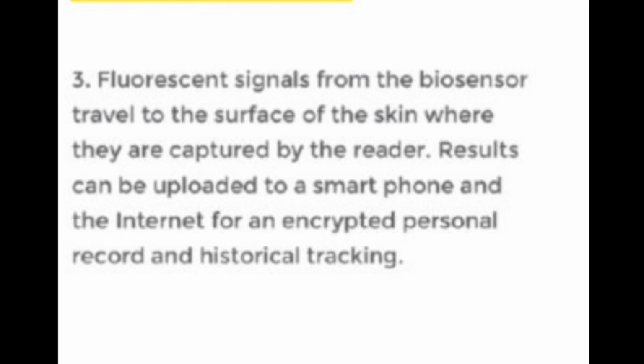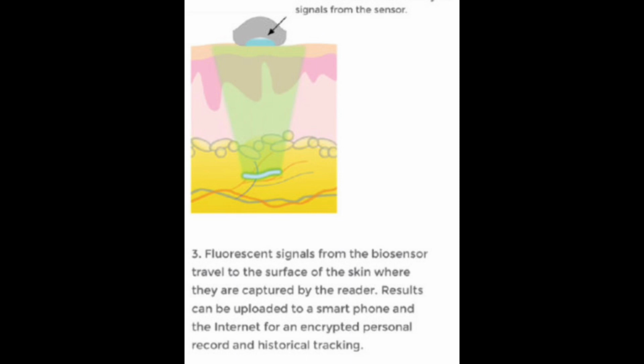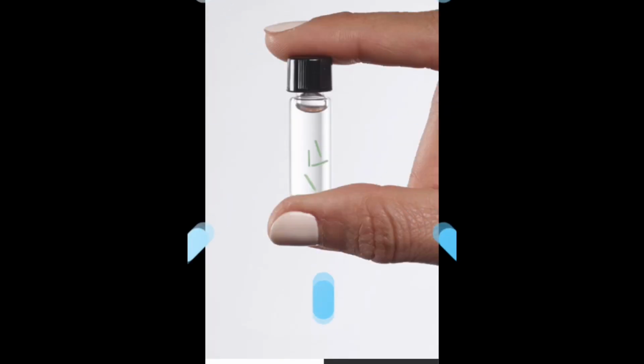One of the key features for our sensor to be able to overcome this foreign body response is this microarchitecture of porosity. These interconnected pores within the small hydrogel encourage the body to grow healthy tissue throughout the interior of the sensor. It basically mimics what is called the extracellular matrix.